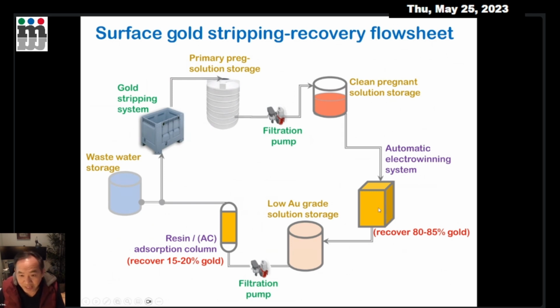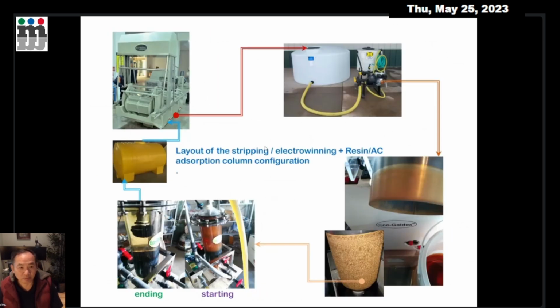And then the depleted solution is sent to what we call the adsorption column. In this step, we not only recover the remaining 15 to 20% of gold, but also clean the solution before we can send it back to recycle. So our wastewater can be recycled through this process. This is the surface gold stripping and recovery flow sheet. And this is exactly the layout of the system.